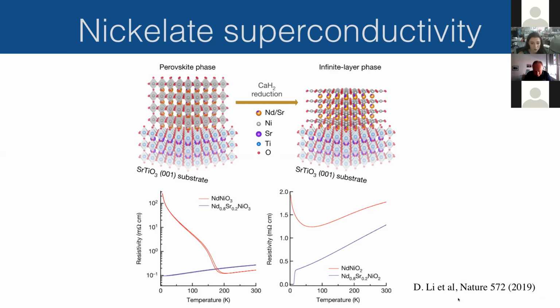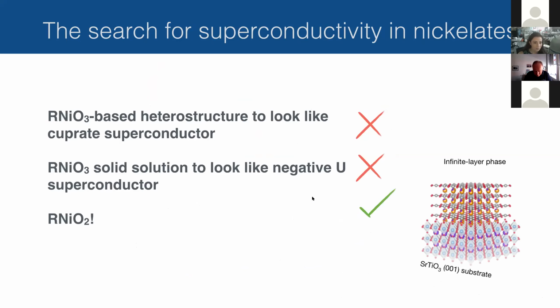But it seems that the superconducting state of the infinite layer nickelates is not very similar to the superconducting state of the cuprates. So to summarize, trying to make perovskite nickelates look like cuprates electronically did not work. Trying to make perovskite nickelates look like a negative U superconductor like BKBO also did not work. But it seems the trick is to go to infinite layer nickelates, and then you get superconductivity. So this is what we talked about.